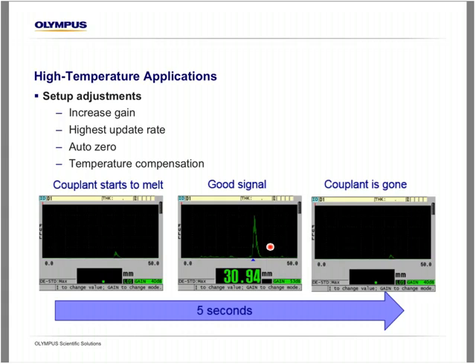But there are some tips we recommend when measuring high temperature. You want to increase the gain about 5 or 6 dB to help get a strong enough signal when you couple on. You want to max out the update rate so that you can make the measurement as fast as possible. You also want to use that auto zero feature that we talked about. You want to use that often because it's going to compensate for the change in sound velocity in the delays.